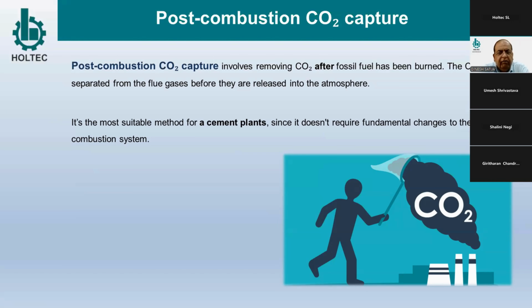In our chimney, we can see CO2 emission is around 18 to 22% CO2 from the cement plant chimney. So if we attack that, that is, after the fuel is burnt and CO2 is finalized, then we capture CO2 from there. This method is most suitable for cement plants because fundamental changes required will not be much.